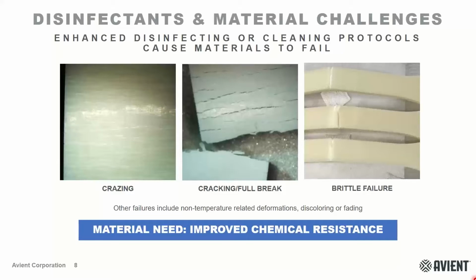And so in the image on the right, you can see this is one that actually failed relatively quickly. There's not a ton of crazing that you can see. So this is a relatively fast failure that led to just a brittle fracture. And so overall, you can see that, in the short time scale of this lab experiment, these materials are failing, and there's overall a need to improve this chemical resistance.